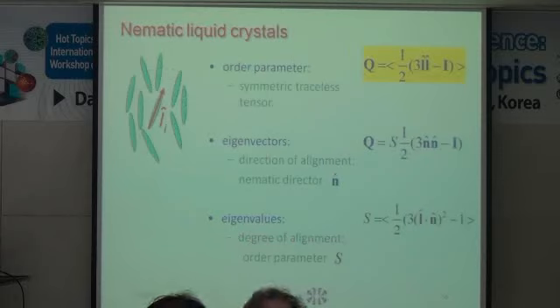So this order parameter tensor is written, in a uniaxial case where the system has cylindrical symmetry, in terms of the scalar order parameter and the director, this nematic director, that's the direction of average orientation, and the eigenvalue S gives some measure of how well things are aligned in that direction. And I want to stress this because these quantities will be appearing subsequently.